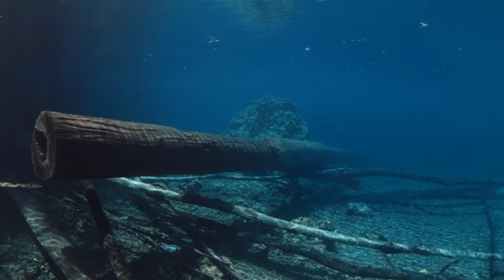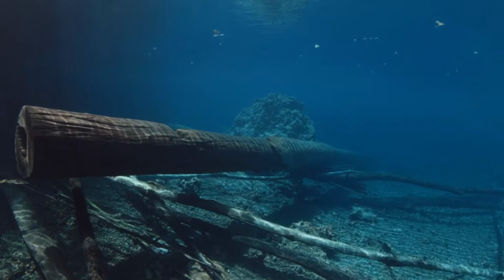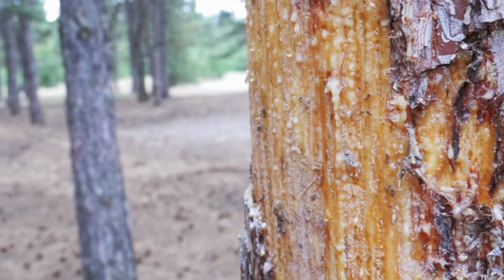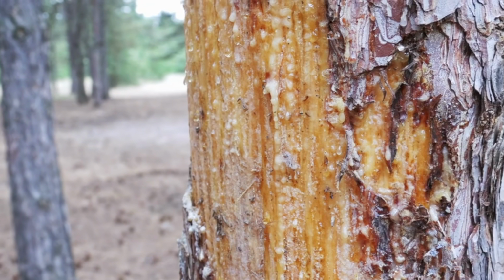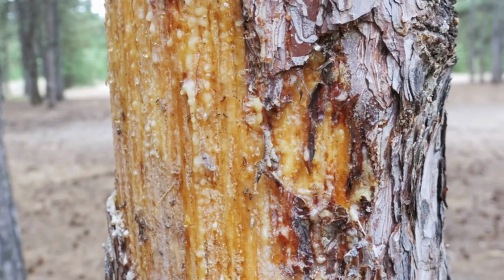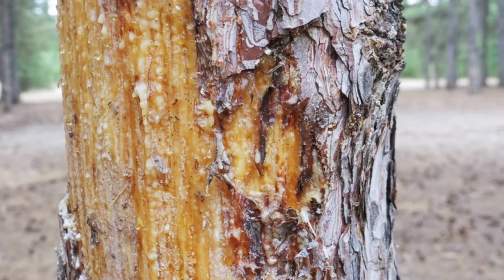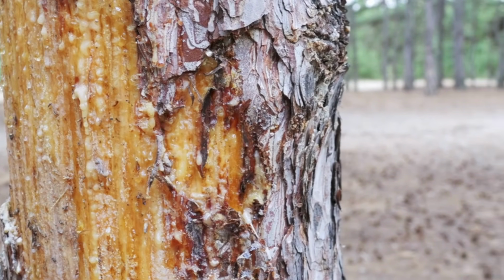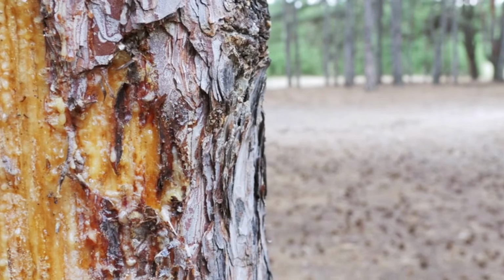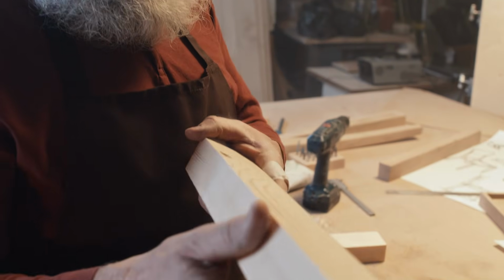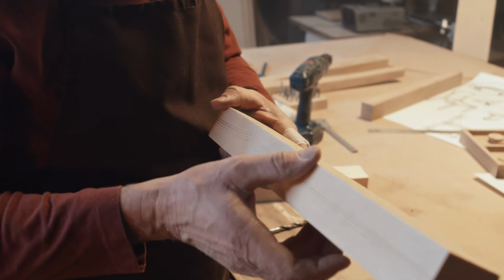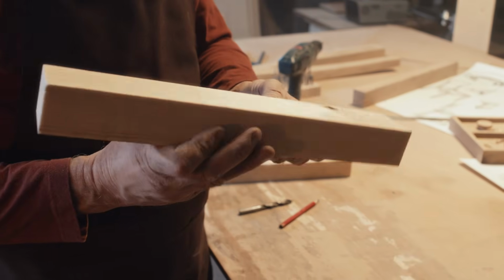Lignum vitae contains up to a quarter of its weight in natural guaiac resin, a waxy, self-lubricating oil that permeates the entire cell structure of the heartwood. This resin makes the wood not only impervious to water penetration, but actually self-lubricating under friction. Shipwrights discovered that lignum vitae could replace metal in one of the most demanding applications on a vessel, the propeller